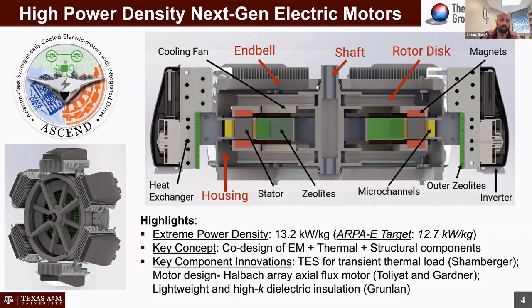Overall, some key components of the system that I've not mentioned include the lightweight, high thermal conductivity dielectric insulation, and this is a polymer nanocomposite we've achieved. Professor Jamie Grunlan's leading that effort, and we've achieved, I believe, thermal conductivity on the order of about 0.8 to 0.9 watt per meter Kelvin of this polymer nanocomposite, with the goal to be reaching between 1 and 2 watt per meter Kelvin.